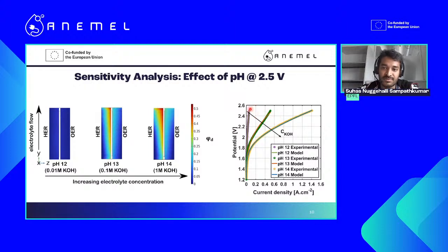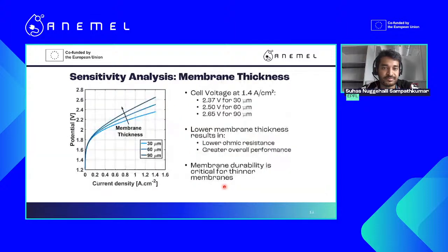So pH 12 is really pretty much no hydrogen evolution, or really low, and perhaps pH 13 could come into this classic alkaline domain. But then I think, any simulation further, any concentration less than pH 14, it's quite tricky to achieve with these standard commercial materials.